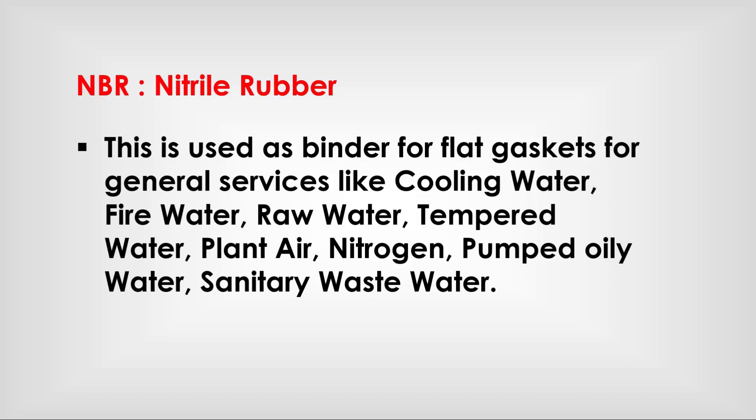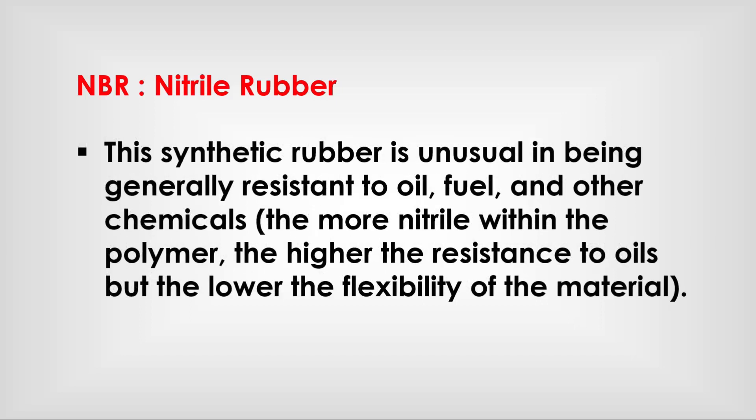NBR (Nitrile Rubber) is used as a binder for flat gaskets in general service such as cooling water, fire water, raw water, tempered water, plant air, nitrogen, pumped oily water, sanitary wastewater. This synthetic rubber is generally resistant to oil, fuel, and other chemicals. The higher the nitrile content within the polymer, the higher the resistance to oil but the lower the flexibility.